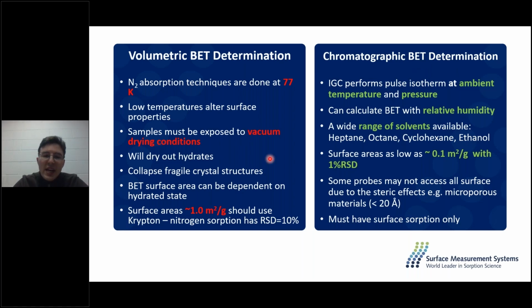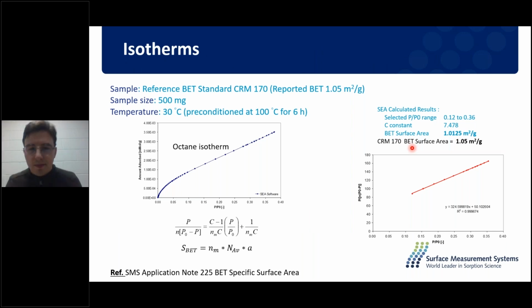On this slide, you can see some of the drawbacks that I have highlighted for the volumetric technique. And there are a few other benefits that we find with the chromatographic technique. I can do BET determination as a function of many different solvents. I can do a surface area determination with hexane, octane, cyclohexane, many different probe molecules. And I also have the ability to use humidity during this measurement as well.